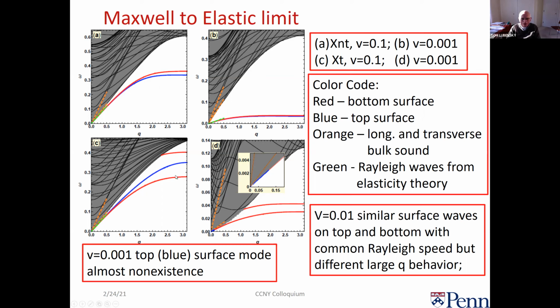When I have a topological lattice, the red side is the bottom ones where I know I have more modes. And as I turn on the next nearest neighbor forces, one of the modes becomes an optical mode. And then on both surfaces, I have a propagating acoustic surface mode. But when I go to very small values of the next nearest neighbor force, then the blue, that's the top surface, has only a very small region where there is a surface mode. It has the same slope as the surface mode of the bottom mode.